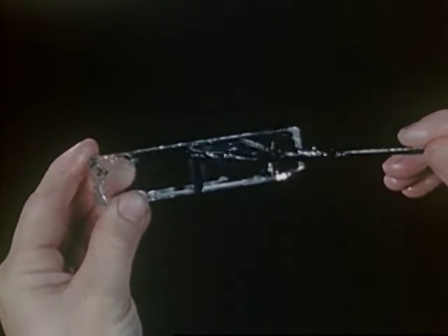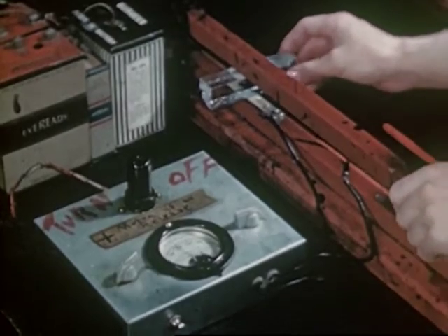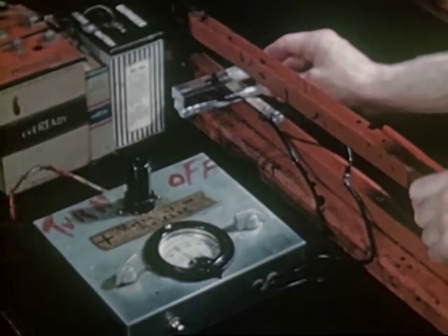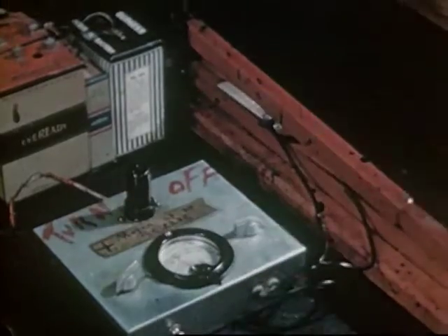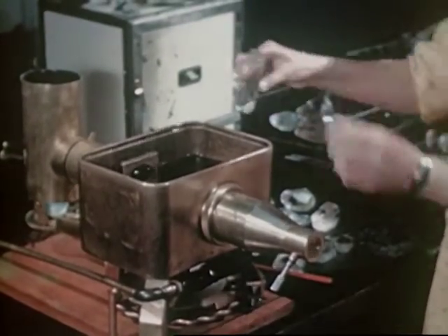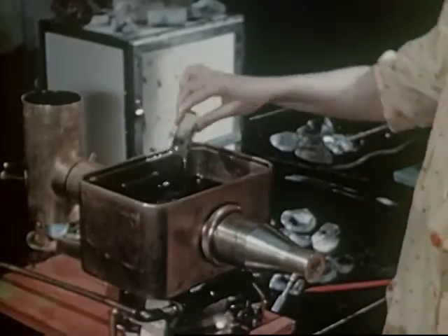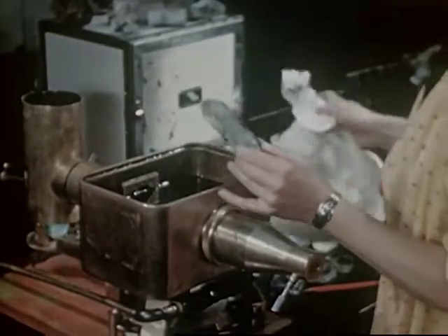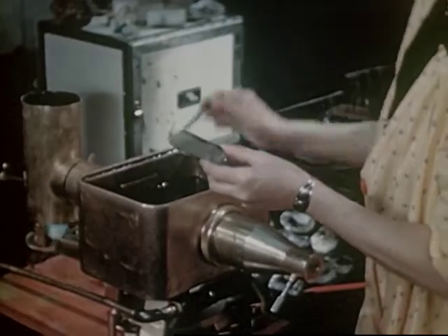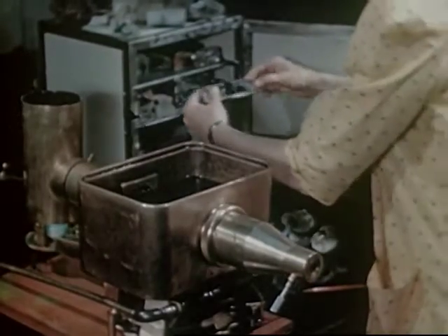As a first step, we need to identify the electrically negative and positive faces of the quartz bar. This is done by squeezing it gently under a lever arm and measuring the electrical charge on a vacuum tube voltmeter. The second step in lining up the quartz for cutting is made in a conoscope. Direction marks are again made on the bar, and it is placed in an electric oven to be heated in preparation for mounting.